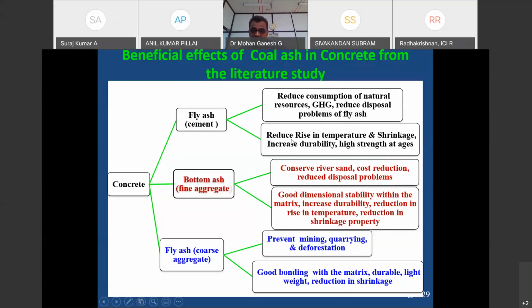On the other hand, the indirect benefits: by using a larger quantity of fly ash, it reduces the rise in temperature inside the concrete. So fly ash concrete or high volume fly ash concrete is recommended for mass concreting. Further, it reduces shrinkage, increases durability, and it can gain strength at later days, 56 days or even 90 days. At VIT, we have even done compressive strength up to 365 days.